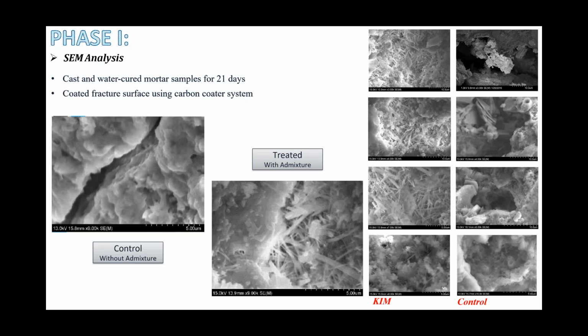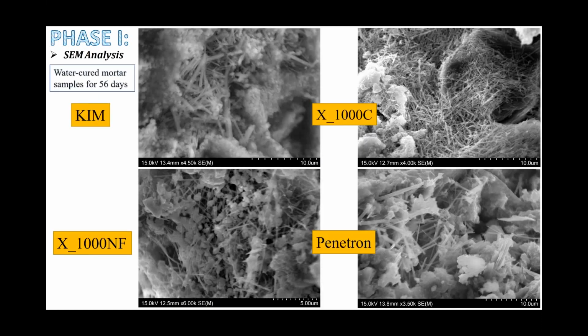I went even further, because there are waterproofing admixtures or crystalline admixtures, so I extended the study to use 4 different types of these admixtures which are commercially available. As you can see, the KIM product is from Kryton, an international company here in Vancouver, and also 2 different products from one company and the other one from Penetron. As an indication, all of them showed the growth of crystals inside.